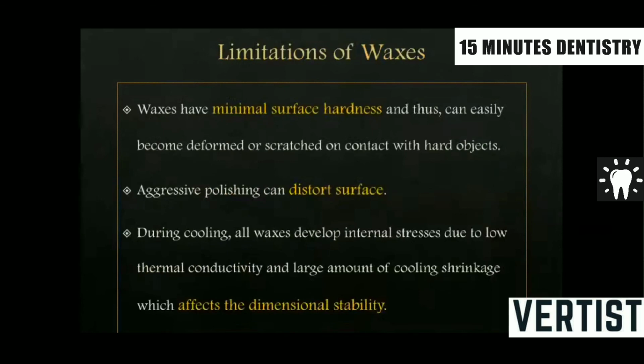These waxes have a limitation, that is that waxes have minimal surface hardness, so they can be easily deformed. If they are aggressively polished, then they will distort. During cooling, all waxes develop internal stresses due to low thermal conductivity and large amount of cooling shrinkage, which affects the dimensional stability of the waxes, which might be seen in the restoration or the appliance you give to the